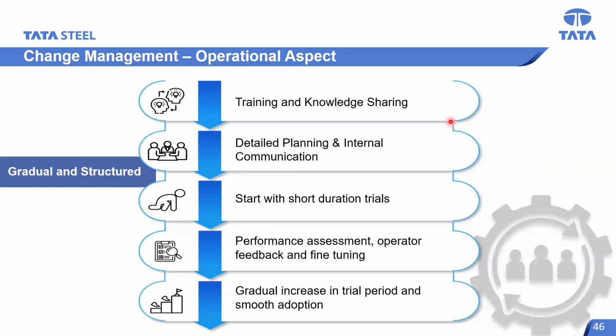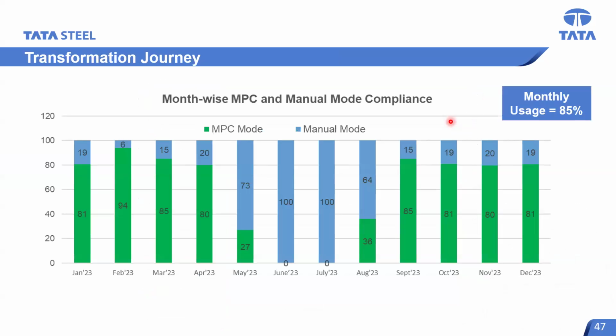After this, we started the trial first for a few minutes, then a few hours, a few coils, then one shift, then a few shifts. Then gradually we increased, and we took the feedback from the plant team and the operating team, incorporated their suggestions, and did the necessary fine tuning. By the beginning of January 2023, MPC had become the normal default operation mode.